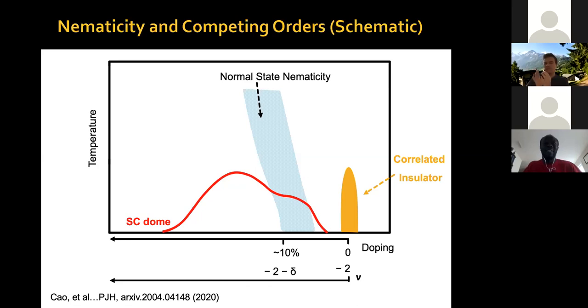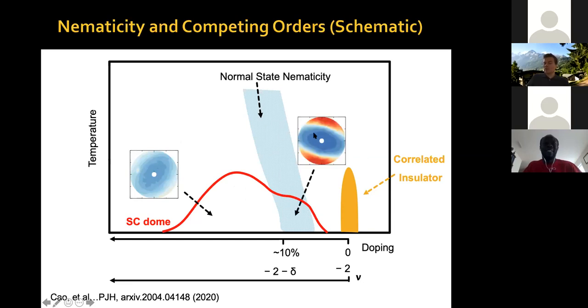And this manifests itself in the behavior of the critical parallel magnetic field, and also in the behavior of the critical current versus parallel magnetic field angle and direction. Everywhere in this dome, including regions where above there's no nematicity, there is an ellipse, and the major axis of the ellipse can rotate smoothly with doping. However, when we get to the doping where this region of normal state nematicity is, we see a much faster rotation of the major axis of the ellipse.